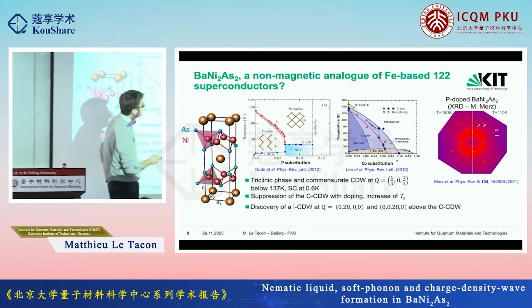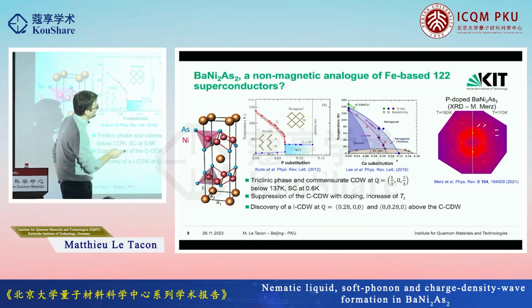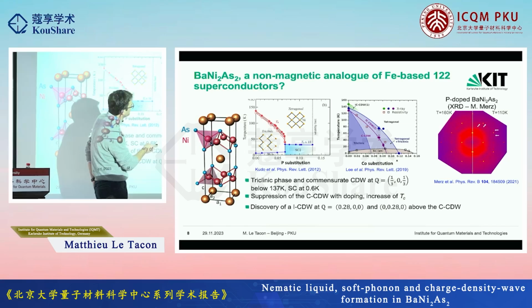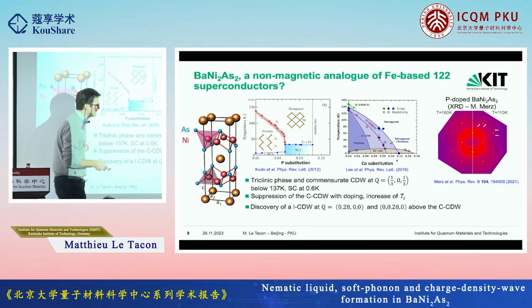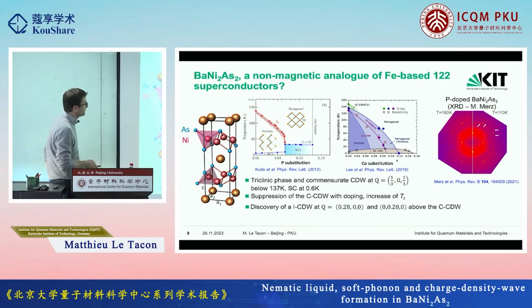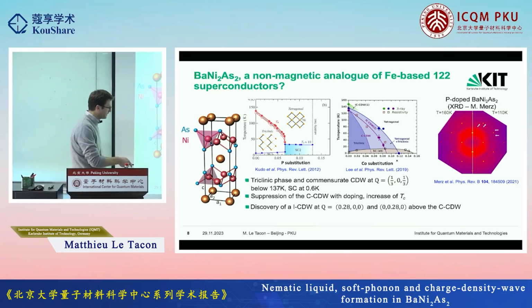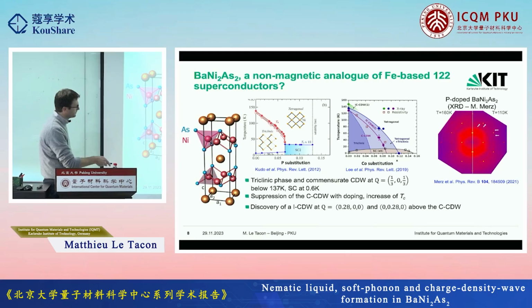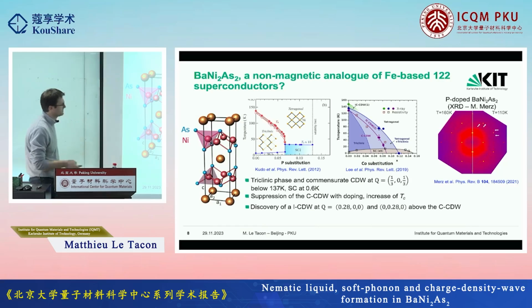So these are X-ray data at 160K and 110K. I'm not sure whether we can nicely see it, but this was measured on an image plate system. You see that when you cool the system down, this is a doped compound, so the temperature is a bit lower, you essentially have these two sets of satellites, shown by the white arrow, that appear around the main Bragg peak. So you can nicely see this modulation. And this corresponds to a charge density wave, which again is incommensurate, 0.28,0, and has another satellite at 0,0.28,0, and it's above the commensurate charge density wave.